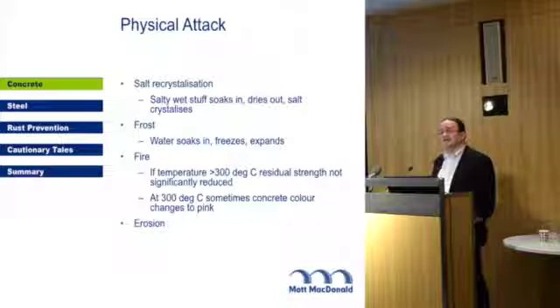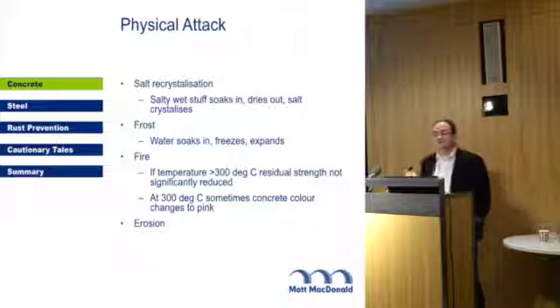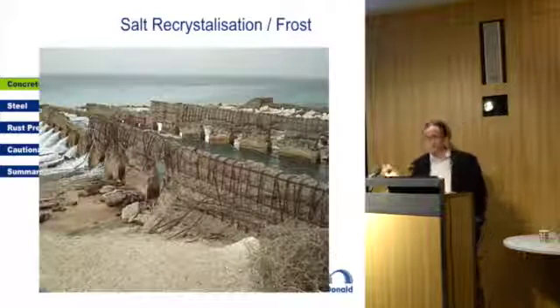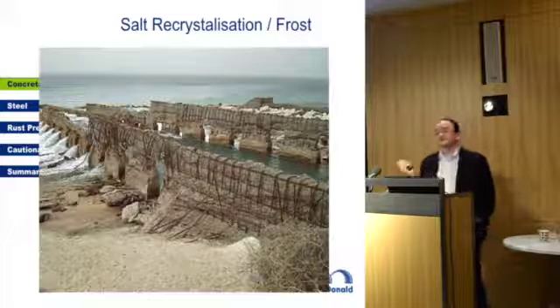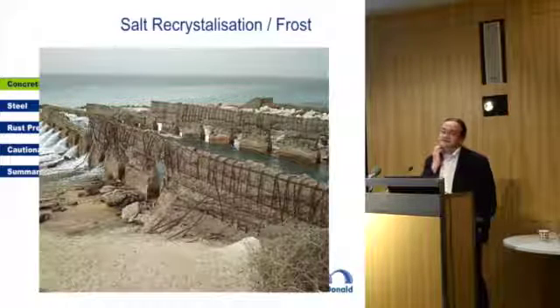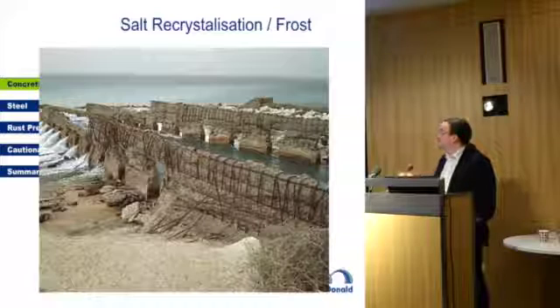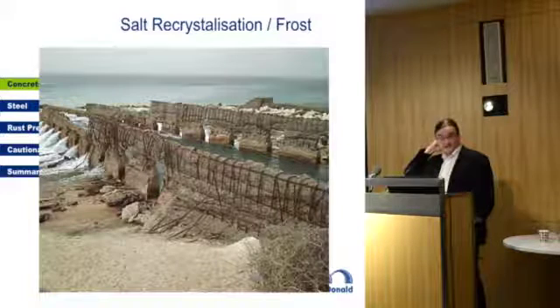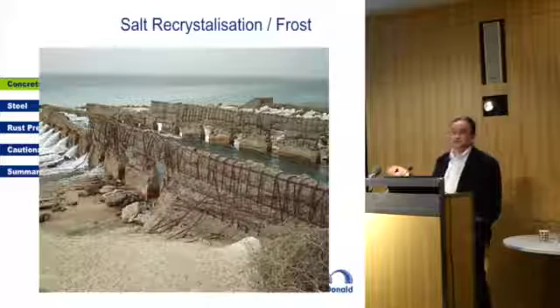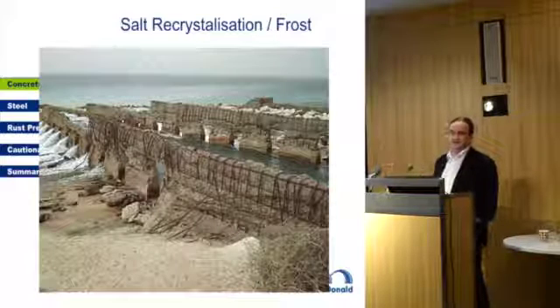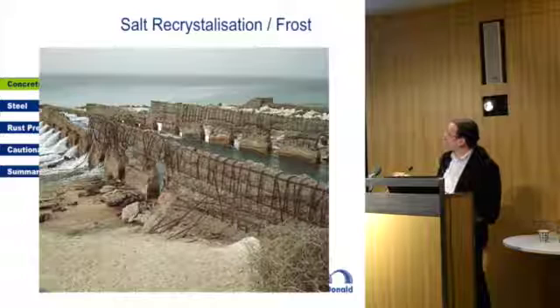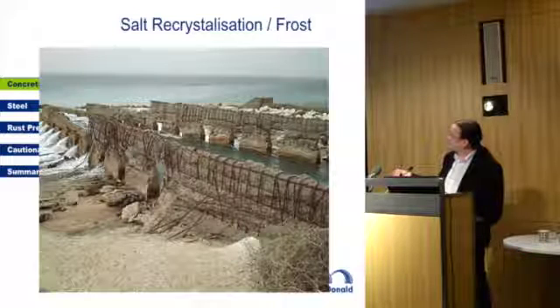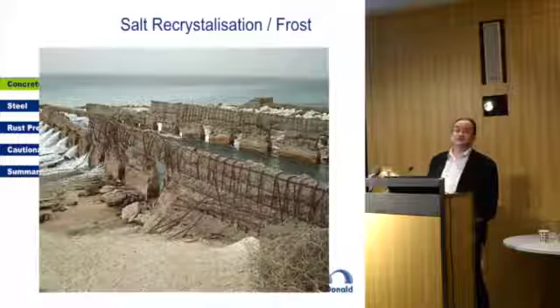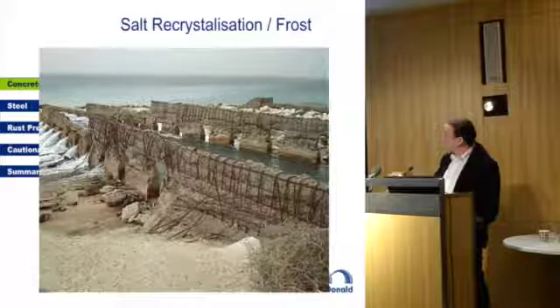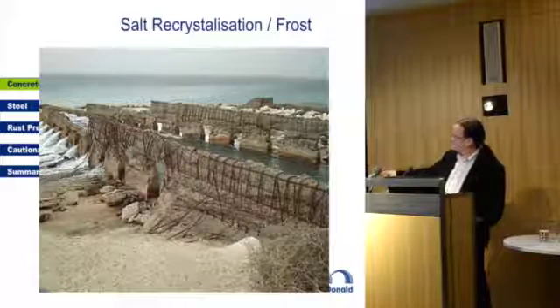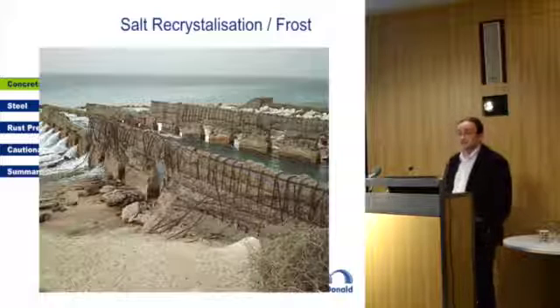And concrete, despite it being hard and lovely and wonderful, it will wear away. That's a seawall in the Middle East suffering from salt recrystalisation. It's about 3 years old. Ambient temperature is about 40 degrees. The sea is slightly saltier over there than it is over here because it's 40 degrees and it's constantly evaporating. And we know it's not the reinforcement corrosion that's causing the problem because, to be honest, we can see all the reinforcement and it's not that corroded and the concrete's still going on behind it. The cover is that slightly darker browny stuff compared to the sand on the beach. It takes about 3 years for that to happen.